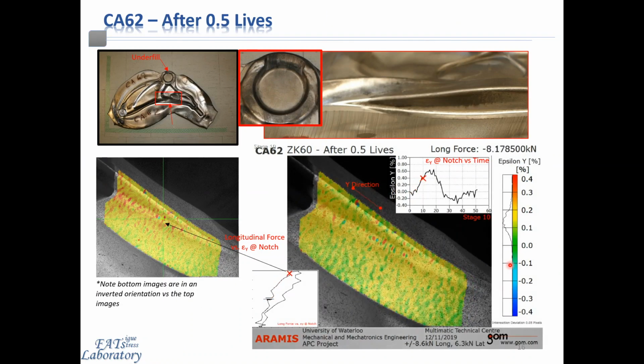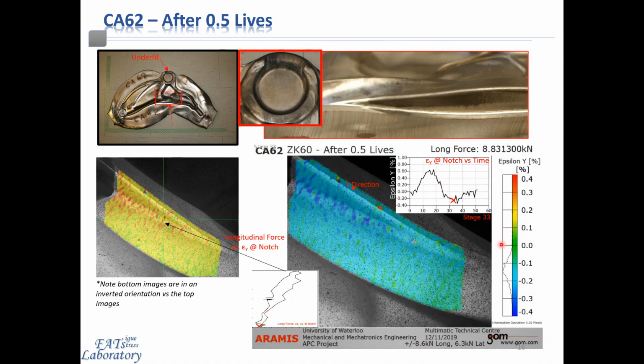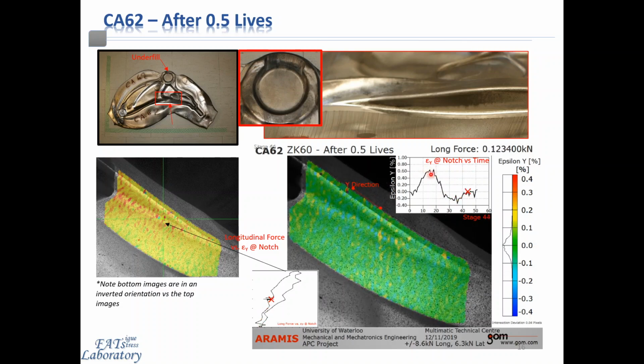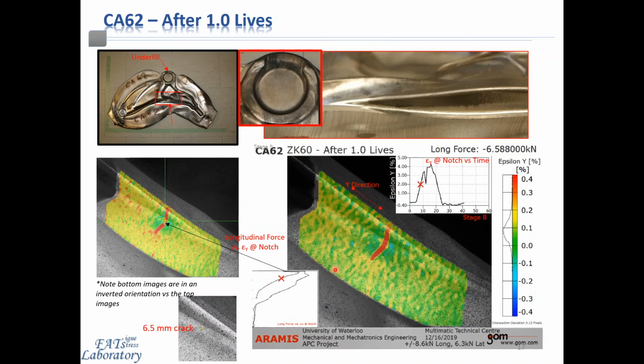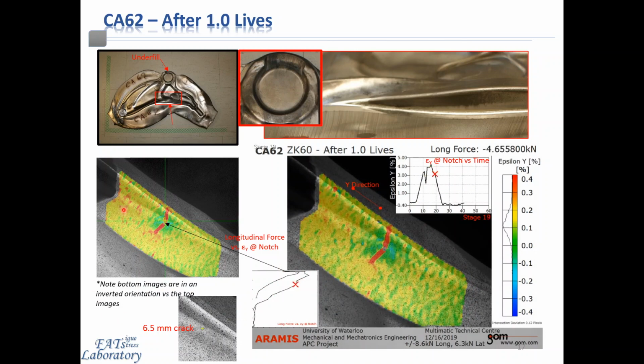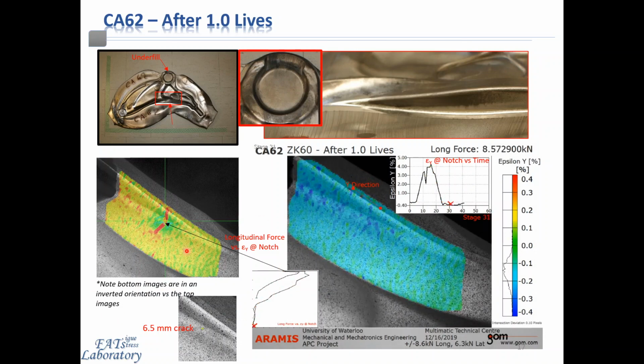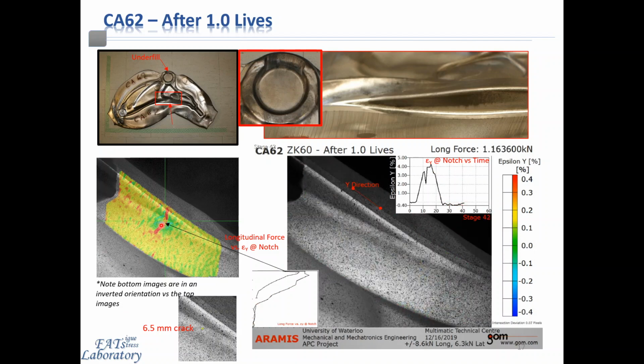Now, after accumulating 50% of the target life in terms of number of cycles, we can see that the peak strain observed in tension has increased somewhat to 0.6%, indicated by the peak here, illustrating that a crack is now nucleated at the location indicated at the green crosshairs in the image on the left here. We can see that more area is now being enveloped in the hysteresis loop, indicating more plastic work being done. After 100% of the fatigue block loading, we can easily observe the strain localization indicated here, and we can measure the crack to be approximately 6.5 millimeters in size now. The crack is signified by the region which is showing 0.4% strain at the surface as indicated here.